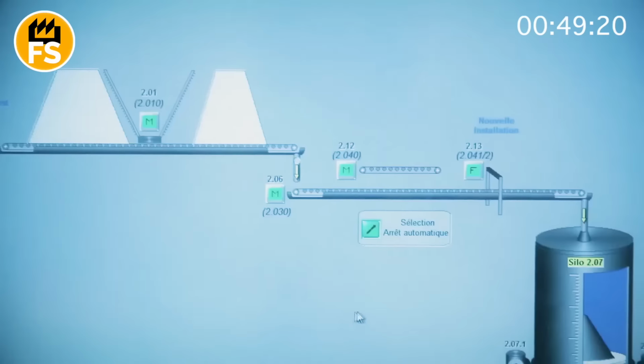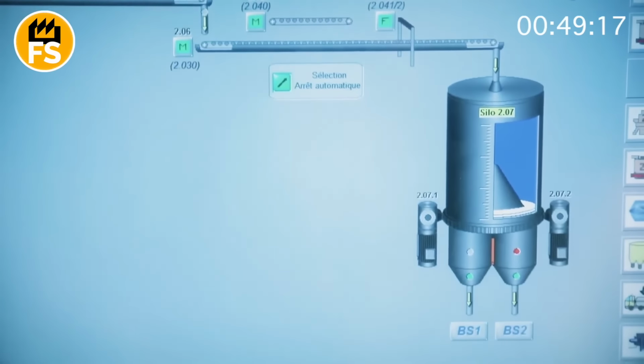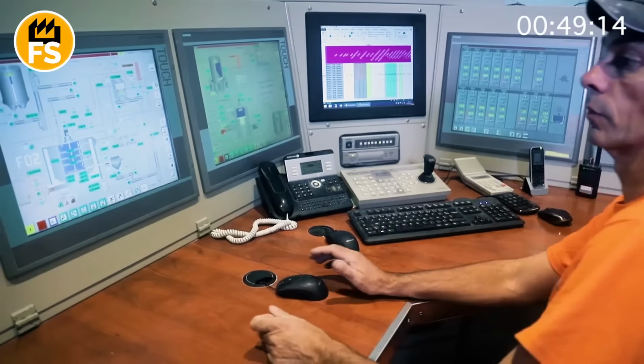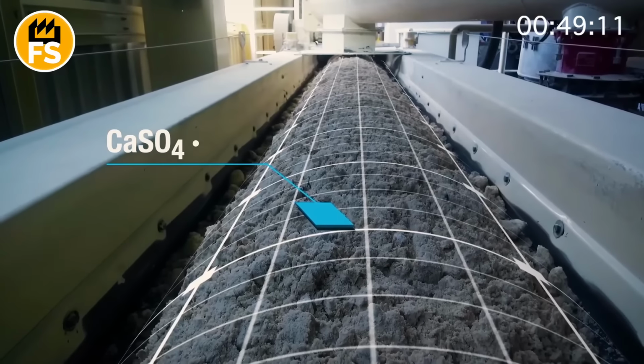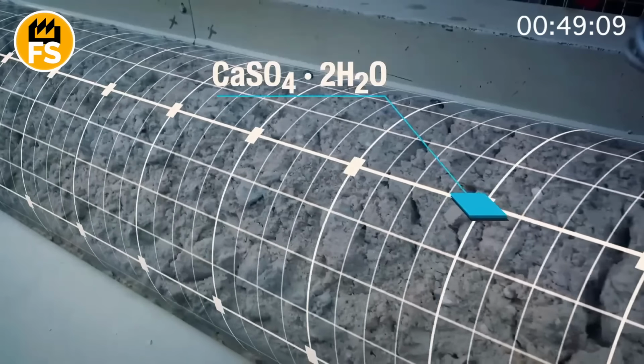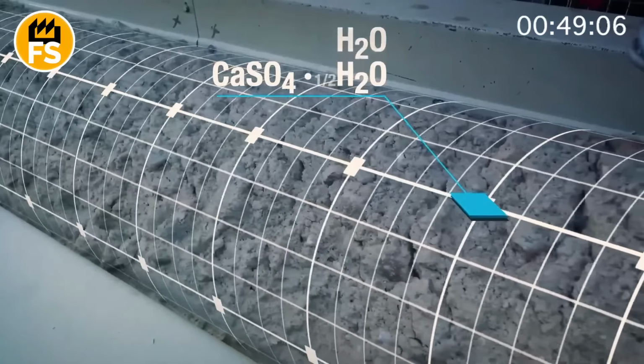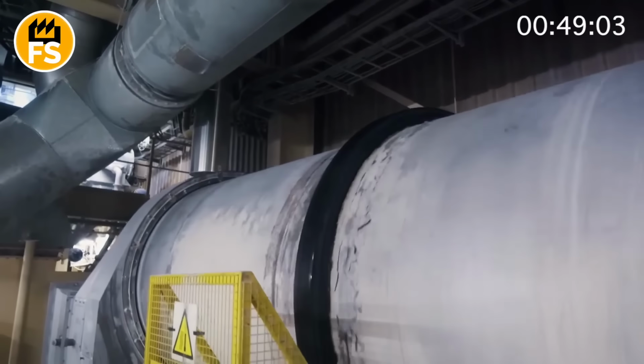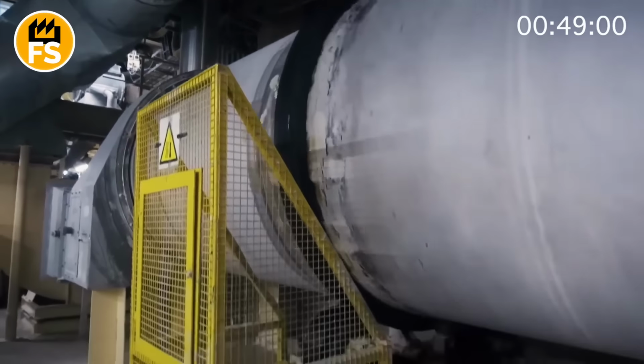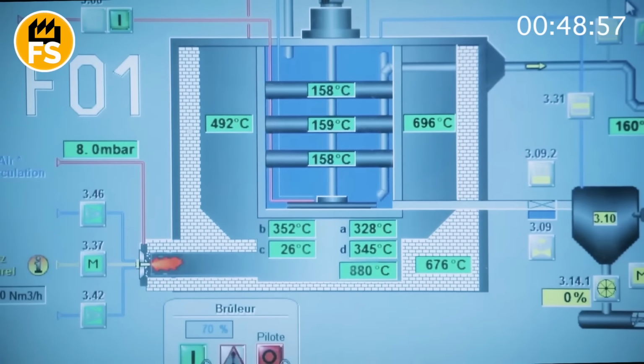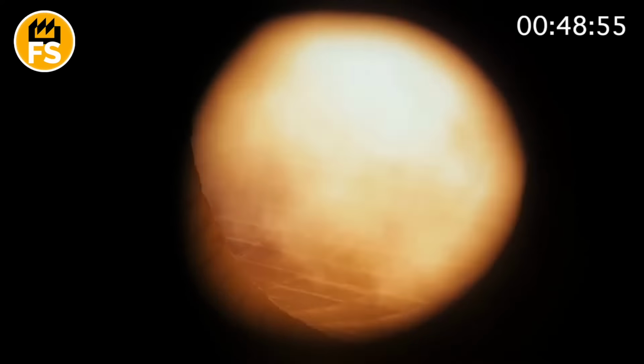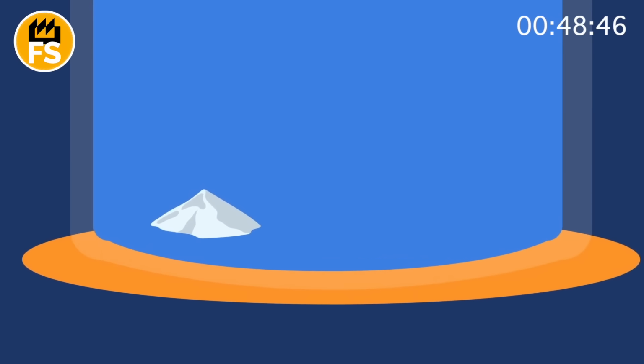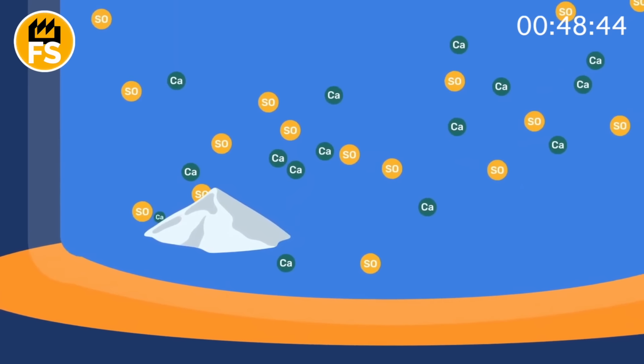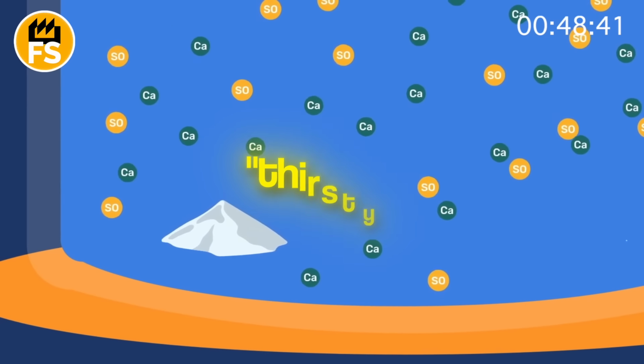The thing is, molecules of water are locked within the crystal structure of natural gypsum. To allow the drywall to harden, this water must be temporarily driven out. For this, the white powder is fed into a huge, slowly rotating furnace. It looks like a giant drum, tilted at a slight angle. Inside this furnace, a very precise temperature of about 300 degrees Fahrenheit is maintained. The gypsum powder, slowly tumbling inside the drum, heats up, and the water bound to it turns into steam and evaporates. Chemically speaking, gypsum turns into calcium sulfate hemihydrate, but in simpler terms, it becomes thirsty.